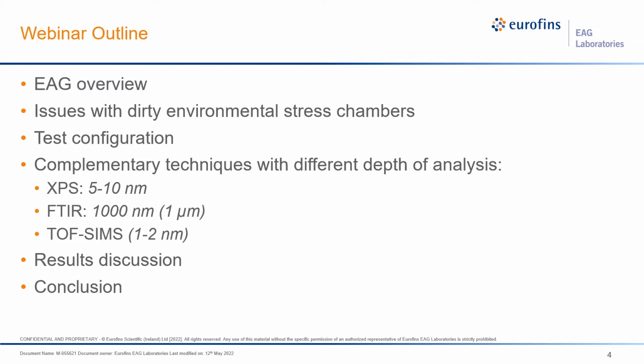And we used XPS, which looks at the very thin layer of the surface up to maybe 10 nanometers, along with FTIR, which looks significantly deeper up to a micron. And then we didn't use TOF SIMS in this particular analysis, but it is another analysis that makes sense for this if we wanted to go look at the contamination present in greater detail. We'll then discuss the results and go through the conclusion.